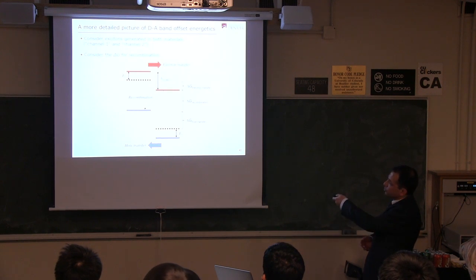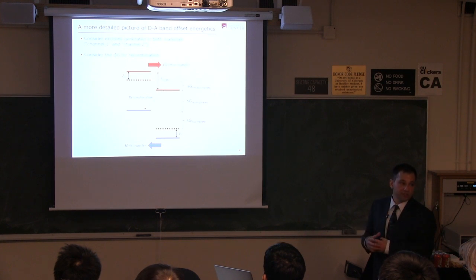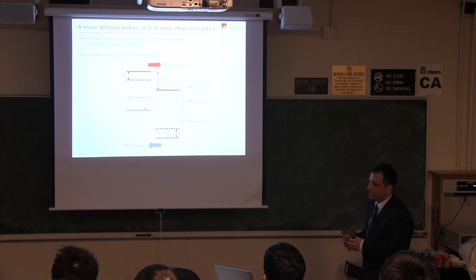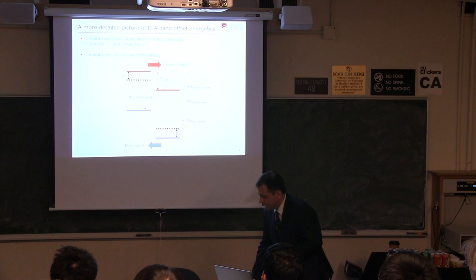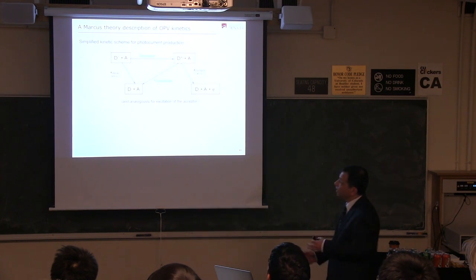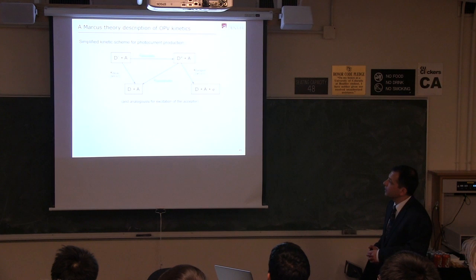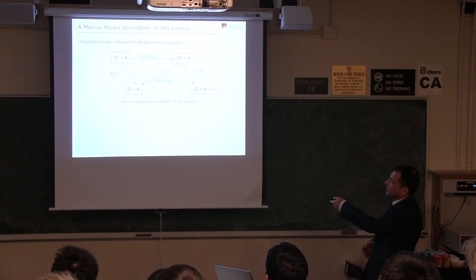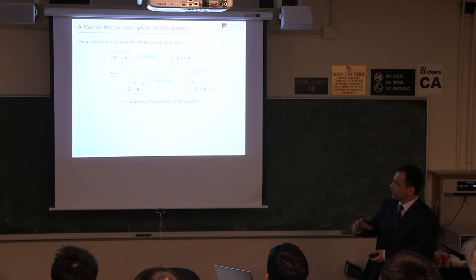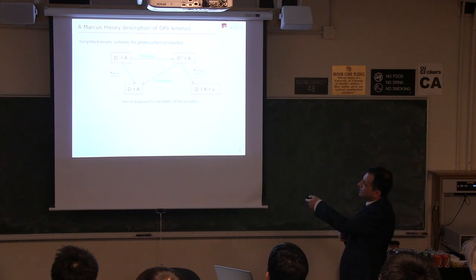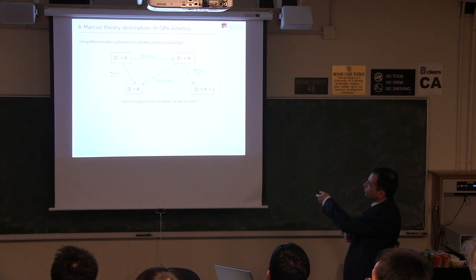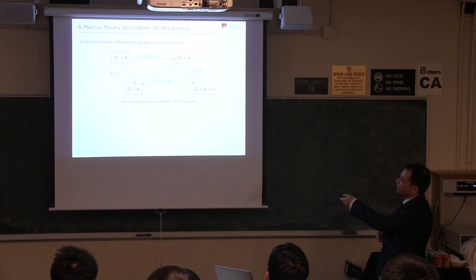So you can see that as you change the band offset, delta LUMO, each of these delta G's is going to change, and it's going to be a pretty complicated kinetic scheme that we have to figure out. So let me take that model and put it into a relatively simple kinetic scheme, where we have initially an excited donor, that's the D star, where the photon came in and was absorbed, in the vicinity of an acceptor. We can have a dissociation process to produce free carriers, D plus A minus, or we can have a luminescence to produce the ground state.